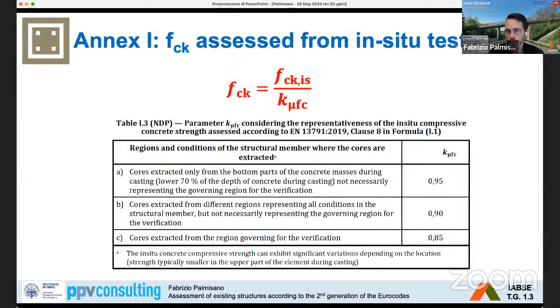Another key point that I would like to highlight, and this is the very last one of my presentation, is relevant to the general procedure to obtain fck. As we know, there is a huge difference between new structures and existing structures. When we're dealing with new structures, the fck, that is the characteristic compressive strength of concrete, is obtained by tests on samples taken during casting. However, when dealing with existing structures, in many cases, we have tests performed in situ, for example, destructive and non-destructive tests. So what we obtain is not fck, but a different value, that is fck in situ, obtained from in situ tests.